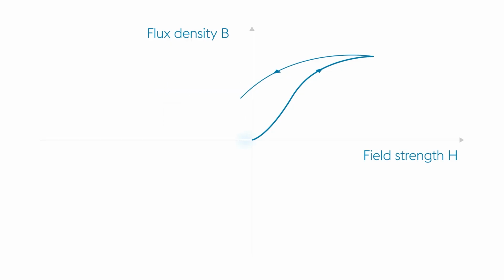Should the current now flow in the opposite direction, the direction of the magnetic field will change, and more dipoles will change their orientation. Magnetization in the electrical steel becomes weaker, and the magnetic effect of the dipoles toward the outside is completely eliminated as soon as a certain field strength has been reached. The magnetic flux density returns to zero. This is called coercive field strength.